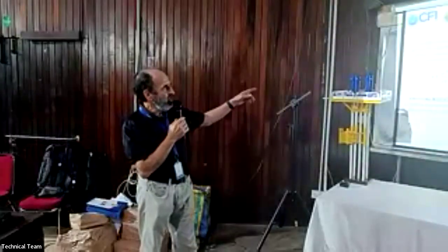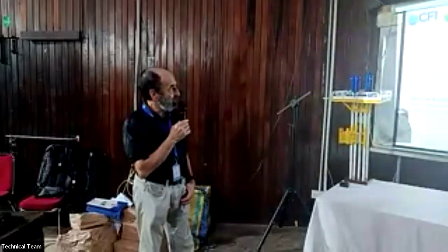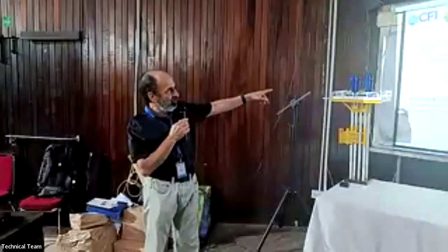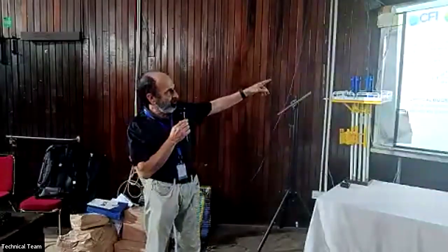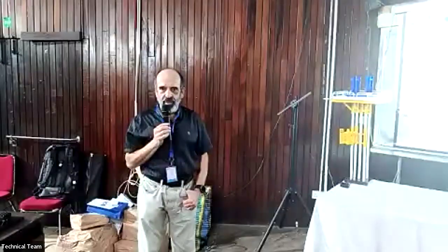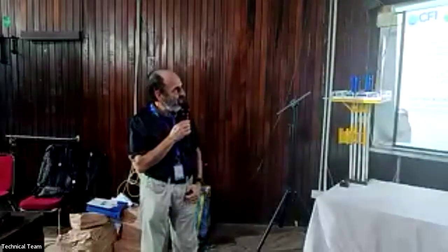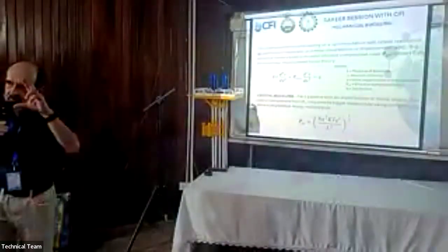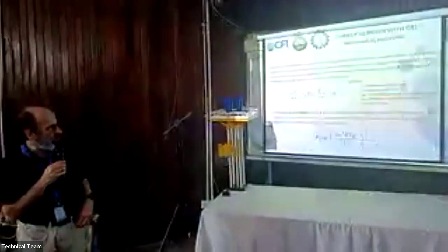But some of the equations I wanted to show relative to buckling: the top equation is basically the EI, which is always used when you look at the compressibility and resistance of steel. So you can see that EI is the moment of inertia times the modulus of elasticity of steel. And then the d to the fourth times nu, that's a fourth differential equation, the fourth level, which is how much the circularity of the pipe is changing if it's becoming ovalized. And then the P_f is actually the effective pressure that that section is seeing, which could cause the buckle.